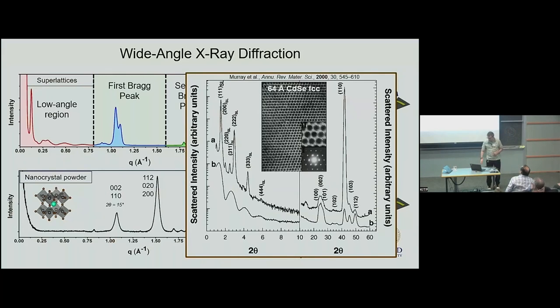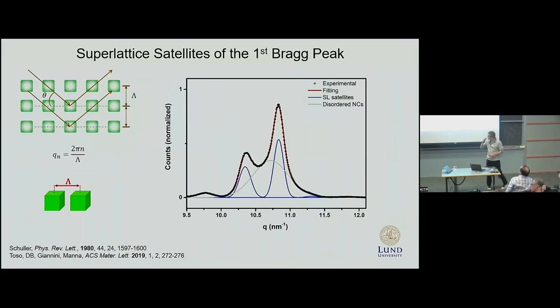So what is the origin of this fine structure? It turns out it's what's called multilayer diffraction. Nanocrystals are well packed, and then the second superlattice periodicity produces constructive interference of X-rays, similar to very thin epitaxial multilayer films.